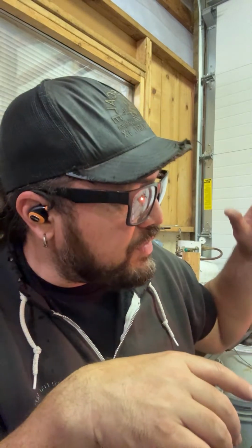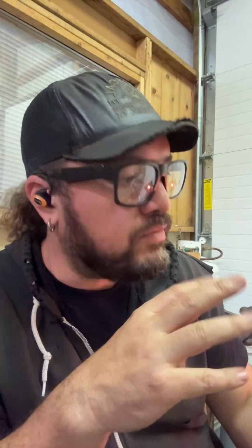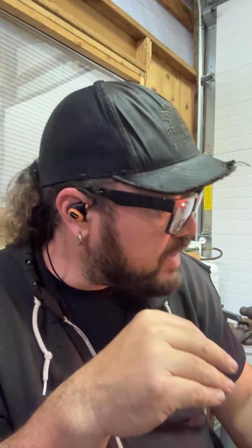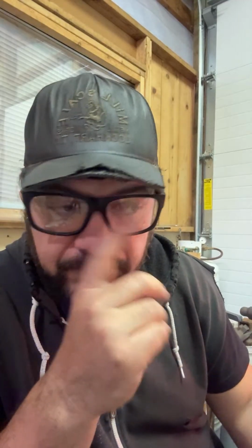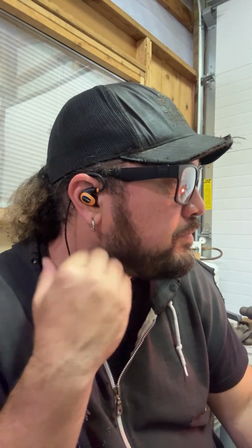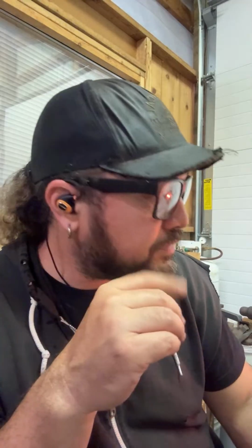So I like to just take my time. Sometimes if I've got other stuff to do, I'll actually turn the forge temperature down even lower, still above critical, but lower, and I'll let it soak for like 30 minutes. Because I'm rushed to get a blade ground, or I have other things in the shop I need to do. That's fine. I'll just turn the temperature down and let it soak for longer. But I still want to age that weld.